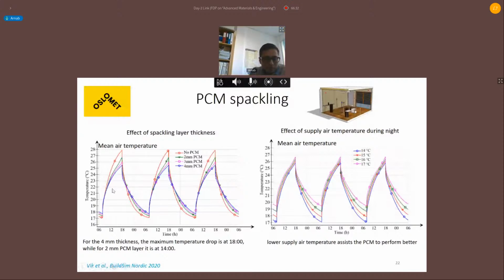Also there is a little shift in the maximum temperature difference. For example, at 4 millimeter thickness, which is the highest thickness that we measured, the drop is at around 6 o'clock, so the temperature drop comes in the later afternoon. But for the 2 millimeter thickness, this arises from the fact that its PCM is shifting, delaying the peak a little bit downward, so that the gap appears more.